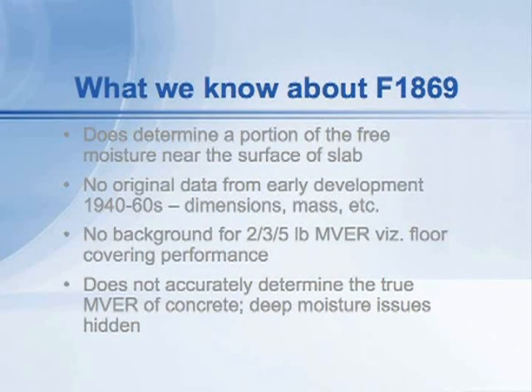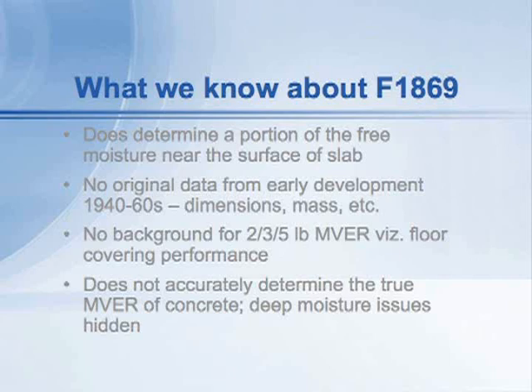So in summary, as far as the calcium chloride test — ASTM F1869 — we know that it does determine a portion of free moisture near the surface of the slab. We know that unfortunately there's no original data, no pedigree to this test from anything that was done in the 1940s, 50s, or 60s. The reasons for the dimensions of the kits, the amount of calcium chloride, or even the fact that we use calcium chloride — there's no scientific basis for all that. We don't know of any real technical background for two pounds, three pounds, or even five pounds moisture vapor emission as having been chosen as the limits for installing floor coverings and adhesives going back 30 or 40 years. We know that the test does not accurately determine the true moisture vapor emission rate as measured by ASTM standard test E96.